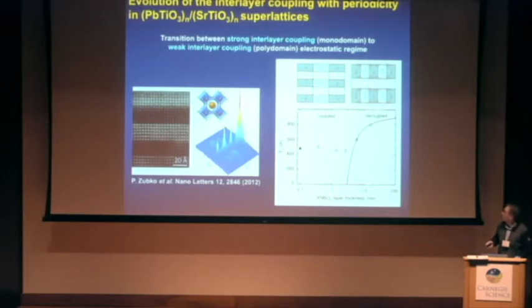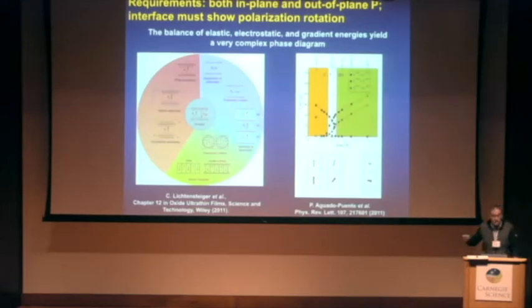But these electrostatic degrees of freedom are not the only thing that are important in this system, because they are also prone to have a polarization rotation imposed by the in-plane lattice constant of the substrate. In particular, a compressive strain favors a 001 polarization, the so-called C phase, while a tensile strain favors an 110 polarization, the so-called AA phase, and in the middle, and very interestingly, in regions very close to the lattice constant of strontium titanate, there is a continuous phase transition, a continuous rotation between the C phase and the AA phase. So there is some tendency for the polarization to rotate.